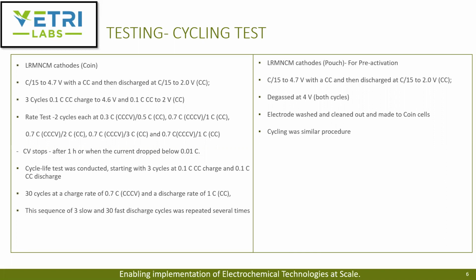After the rate test is done, they start the cycle life test, beginning with 3 cycles at C over 10 charge and C over 10 discharge, then 30 cycles at a charge rate of 0.7C and a discharge rate of 1C. This sequence is repeated.